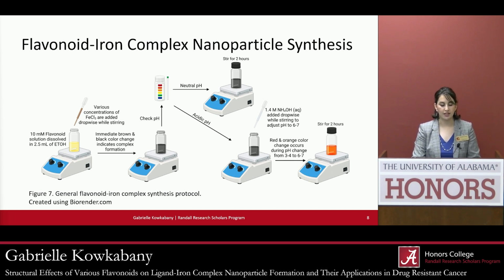However, naringenin did. And so in order to synthesize these nanoparticles, a 10 millimolar naringenin solution was dissolved in ethanol. And then iron chloride was added to it in order to form complexes, which was noted by an immediate brown or blackish color change. And at that point, I checked the pH of the solution and then adjusted the pH using ammonium hydroxide because it was quite acidic, which caused it to change to kind of an orangish reddish color and then allowed it to stir for 2 hours.